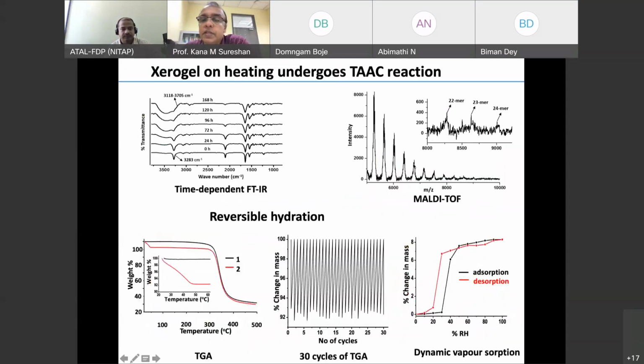So you can see this is the TGA of the monomer, and after polymerization, you can see there is a weight loss. This weight loss is due to removal of water below 50 degrees centigrade at this heating rate. Even at room temperature, it will go, as I said. About 8.4% is the water that can be tapped by this material. And we have done 30 cycles of hydration, dehydration, and this is the data, the percentage every time. Almost 8% you can get.